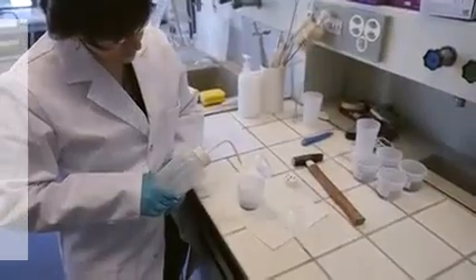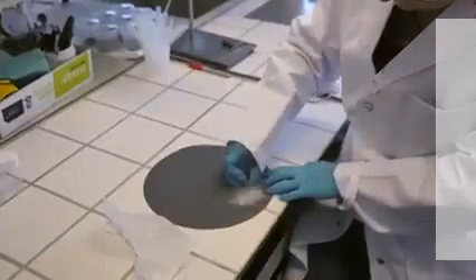First, the sample must be strong enough to be sawn. If your sample is not strong enough, then you will have to stop the hydration using freeze drying or filtration under isopropanol. Once the slice is cut, it must be immersed in a sufficient amount of isopropanol with a 90% purity. It will be necessary to renew this solution regularly the first 24 hours, and then every 24 hours for 4 to 7 days maximum. The disc will then dry in a desiccator for 48 hours. Your slice is finally ready to be put in resin and polished.